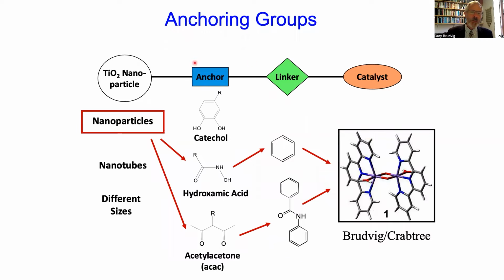So the basic idea for anchoring chemistry is we've got a metal oxide surface, some kind of nanoparticular structure, nanoparticles, nanotubes of various sizes. And we've used insight from nature to design chelating groups such as catechol and hydroxamic acid, which are used as natural products for binding strongly to metal complexes. We've also used inorganic complexes like acetylacetone, or ACAC, chelating groups that can attach to the surface. We link them to catalysts, and one example is this manganese terpyridine complex that Bob Crabtree and I reported previously to be able to carry out the light-driven water oxidation.